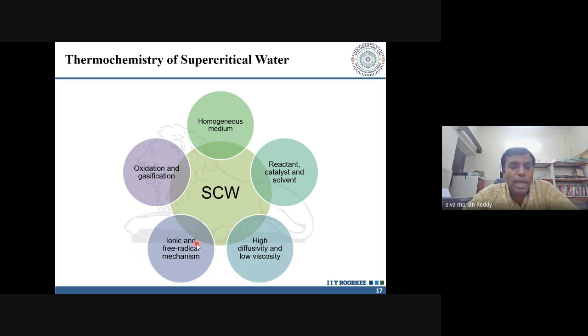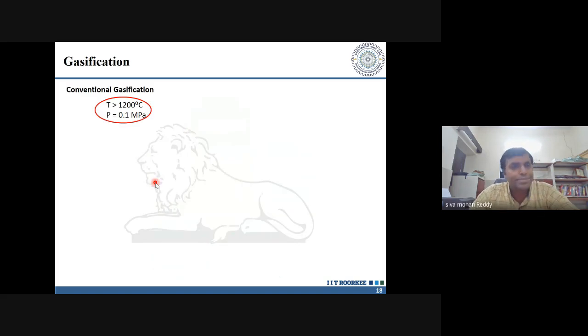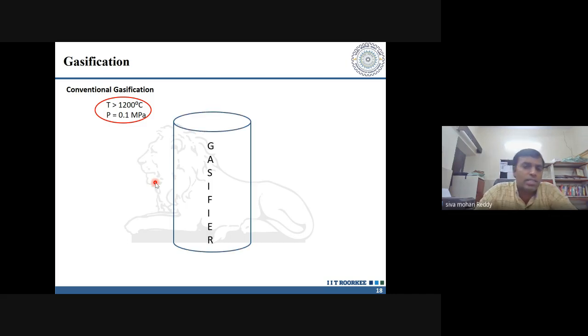Depending upon the operating conditions, the biomass is degraded via ionic mechanisms, or if the operating conditions are beyond the supercritical point, typically more than 500 or 600 degrees centigrade, you have free radical mechanisms. As a result, this technology finds application either in the gasification process or in the oxidation process. Okay, so now let me explain how thermal gasification happens.